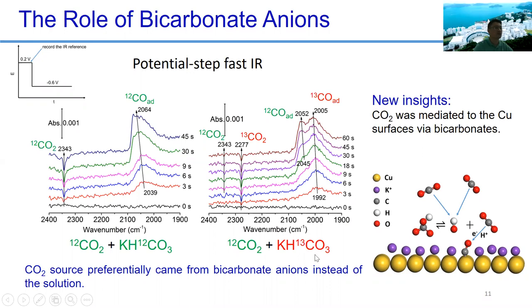If you use this isotope, okay, you can see the carbon 13 in the bicarbonate and the carbon 12 in the carbon dioxide. So in the first 3 seconds, we also see this rising of the carbon monoxide, but the position is different from this previous example. Okay, so much lower number. So that means the carbon monoxide is coming from this bicarbonate instead of carbon dioxide. And at the same time, you can see the carbon dioxide signal also has a different wave number from this, 2343. Okay, so it's coming from a lower number. So due to the carbon monoxide from the carbon 13, right?